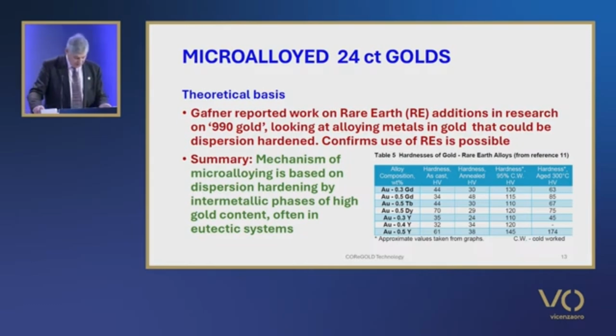The table on the slide shows the hardness values attained for gold alloys containing 0.5 of the alloying metal or less. From this work, it can be seen that the annealed hardness is little different from normal pure gold, although cold work material is much harder and in the range of improved 24-karat gold materials. Age hardening heat treatments are not very effective at these low concentrations, with the exception of the 0.5 weight percent gold yttrium alloy, confirming the view expressed earlier that in the consideration of the solubility data, the heavy rare earths suggested little age hardening was possible at these low alloying levels.